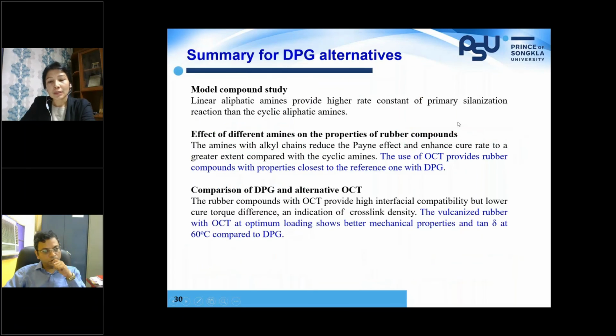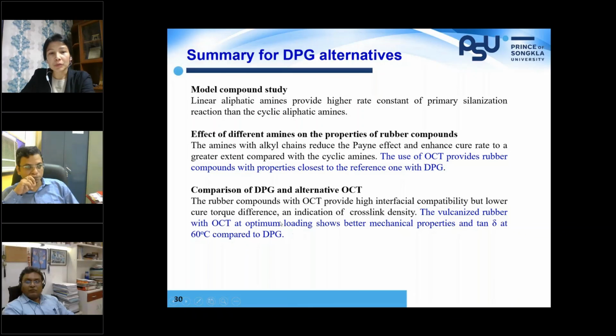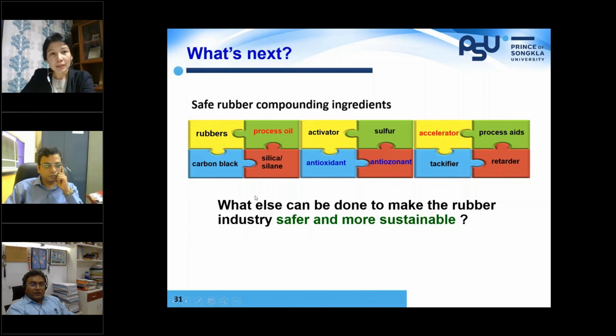compared with DPG. So if I summarize this study, based on the model compound study, linear aliphatic amine works better than cyclic aliphatic, so it gives a higher rate constant of the primary silanization reaction. And the use of octadecylamine provides rubber properties close to the reference compound with DPG, and by having the optimum loading of octadecylamine, we can have even better mechanical properties and tan delta at 60 degrees compared to DPG. So what's next?